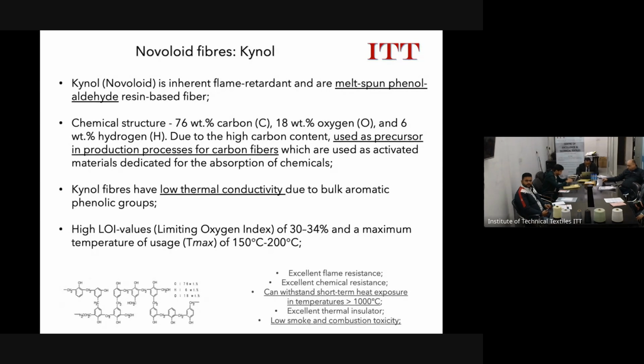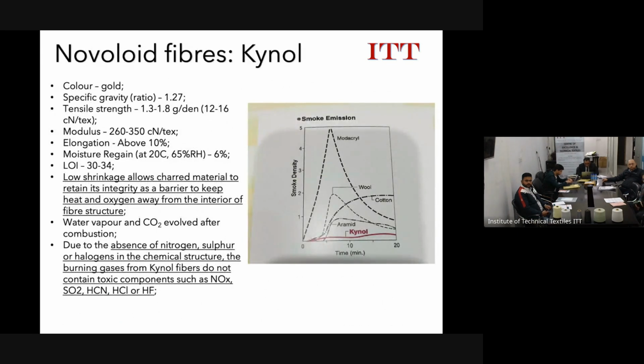It has low thermal conductivity, and it's already being used in certain applications. Again, smoke is interesting for this fiber. If you are looking for something, especially for inside aeroplanes or inside closed areas, Kynol or novolac fiber can be very interesting because the smoke generation levels are very low, shrinkage is very low, and obviously because of the absence of nitrogen and sulfur, it does not contain any toxic components.